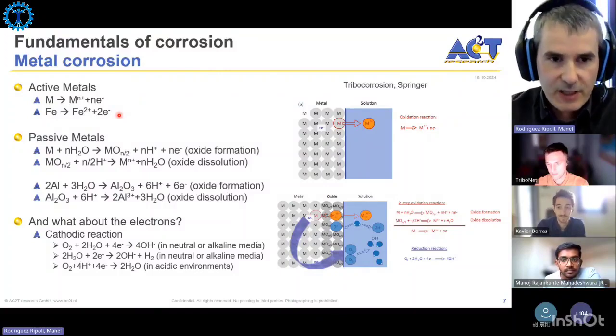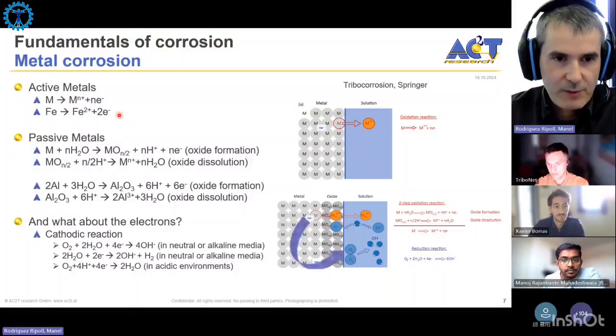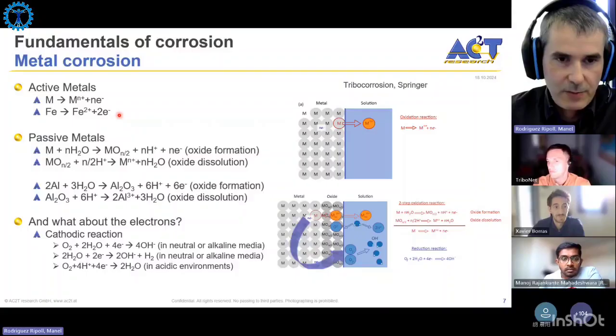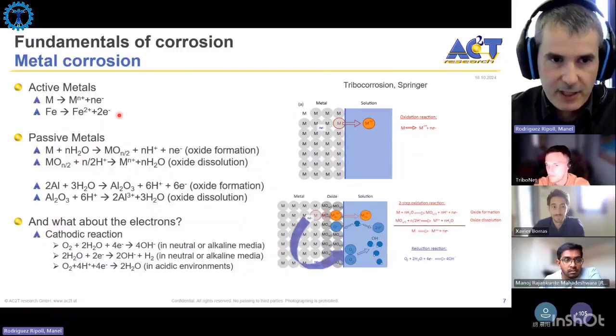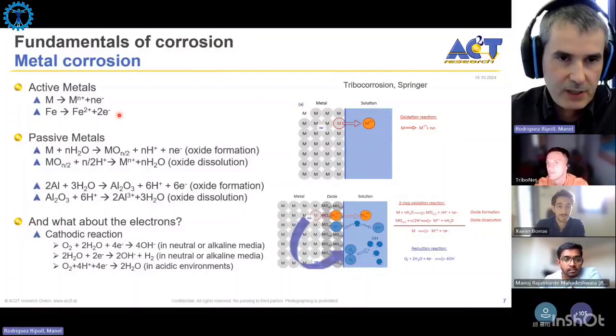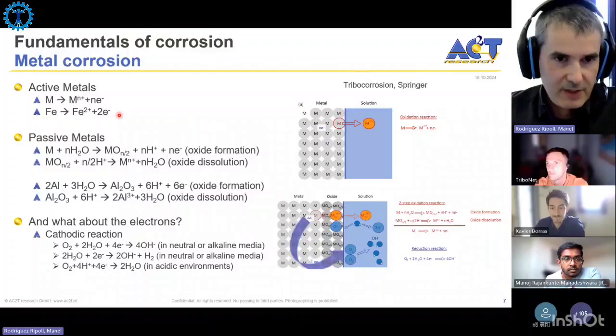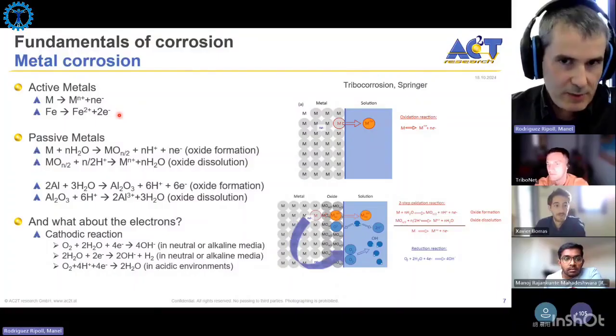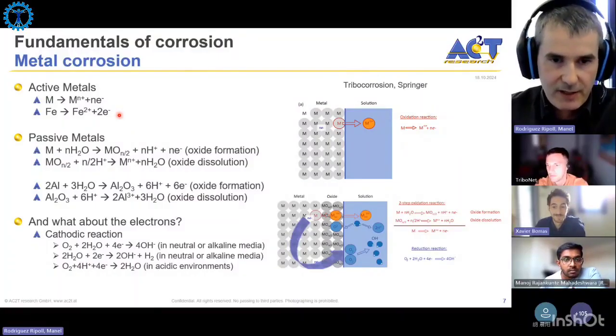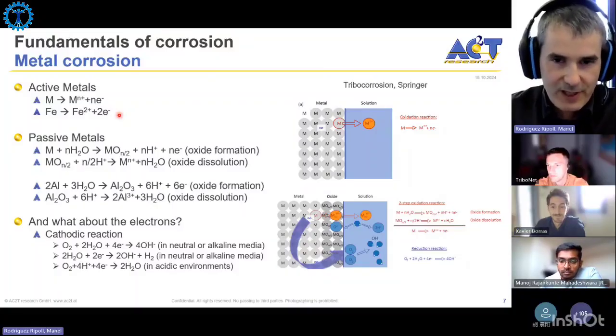And the other question regarding hydrogen is a bit different. This would be current research, but basically hydrogen reacts with metals by embrittlement. Typically you produce hydrogen embrittlement at the grain boundaries and segregations, and here tribocorrosion would arise, since this embrittled surface layer has different properties than the bulk material, and the wear rate will be different if you compare the embrittled layer with the non-embrittled one. But this is slightly different from what I will be presenting today. Today we will be talking about passive metallic materials immersed in an electrolyte. But it is the same idea: a reactive environment and the wear occurring in the reaction layer, in the reaction scale, or in the corroded zone, having different mechanical properties and different microstructures than the rest of the bulk material.